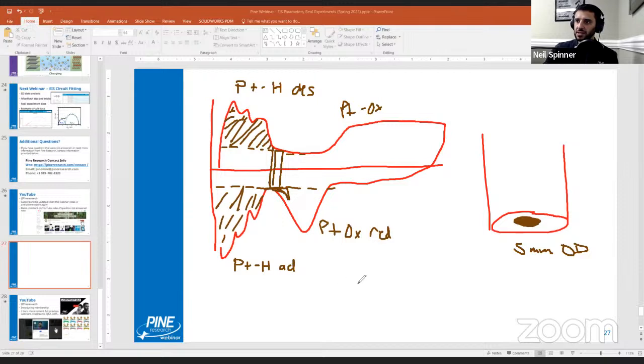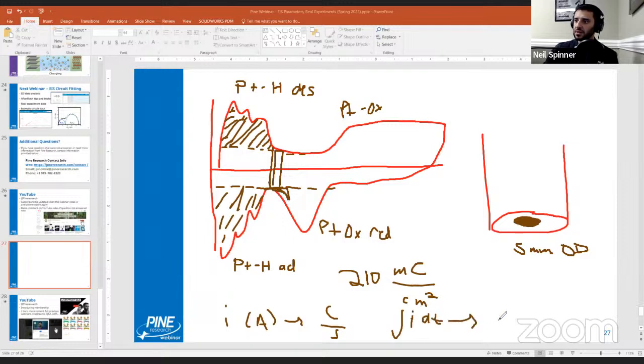And what you do is you relate it to the theoretical ideal. The theoretical ideal is 210 millicoulombs per centimeter squared. Is that right? I think that's right. So coulombs is what you get when you integrate current, right? Current is in amps, which is coulombs per second. So when you integrate current, that's integral of i dt, you get charge, which is in coulombs. Basically you're integrating this, you're getting the surface area.